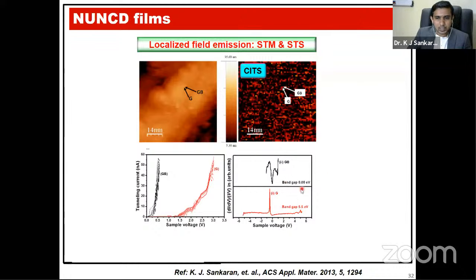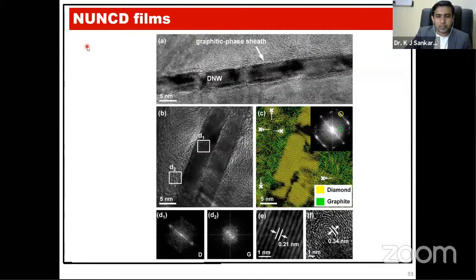So what is in the grain boundaries? In UNCD, we found amorphous carbon, but what is in the NUNCD grain boundaries? So we use TEM. From the TEM image, this is one single diamond nanowire, as you see in the SEM morphology, and covering these diamond nanowires, we can see many wave-like structures. Those are the graphitic phases.